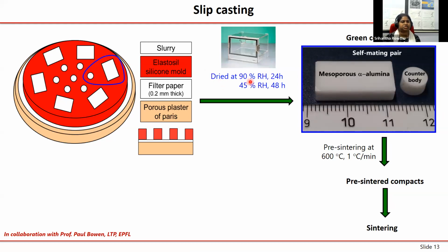The drying happens in two stages. Firstly, you dry it at 90% relative humidity for 24 hours, and later at 45% relative humidity for 2 more days. This allows for very slow drying. Otherwise, if you dry it very quickly, the samples will end up breaking. There will be cracks generated in the sample. After nicely drying it, whatever you are able to demold from these silicone cavities looks like this.